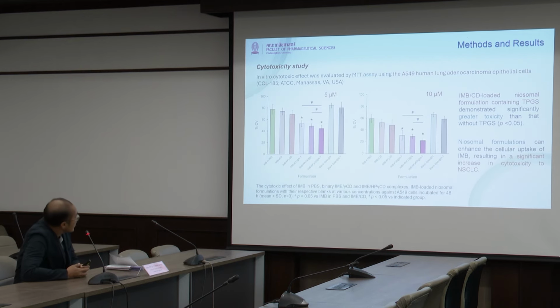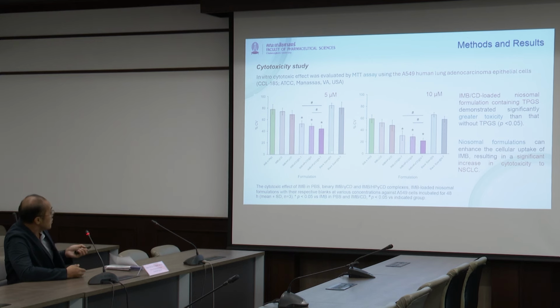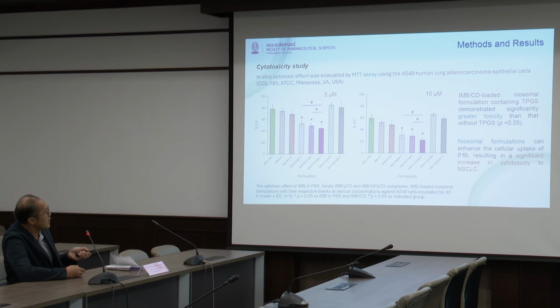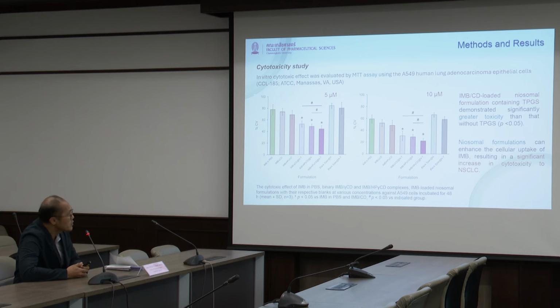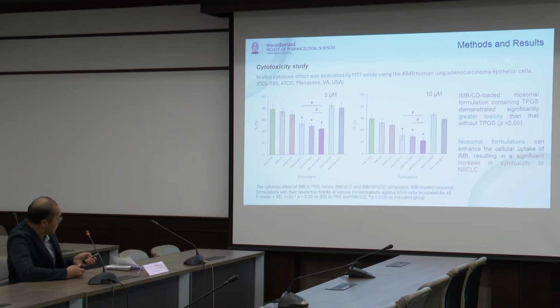Here is the cytotoxic study, where we use our formulations to test and compare with free drug in PBS and with the blank niosomes. We show that our formulations have a concentration-dependent effect. When using a higher concentration, the cytotoxicity is higher. So the most optimum one is the hydroxypropyl gamma cyclodextrin with the presence of TPGS, which can significantly increase the cytotoxicity to the lung cancer cells.